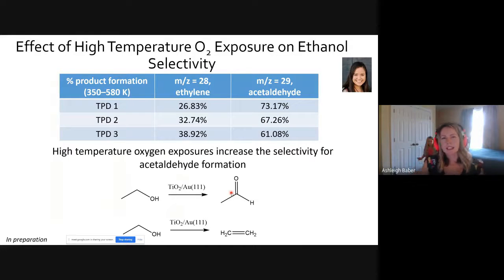One other way we wanted to test this oxygen exposure was to run an opposite experiment where we first started off with a fully oxidized titania on gold surface, and look at the first TPD. You can see the selectivity for acetaldehyde was about 70% compared to ethylene. So this is a larger coverage. It's not that 0.2 monolayers.